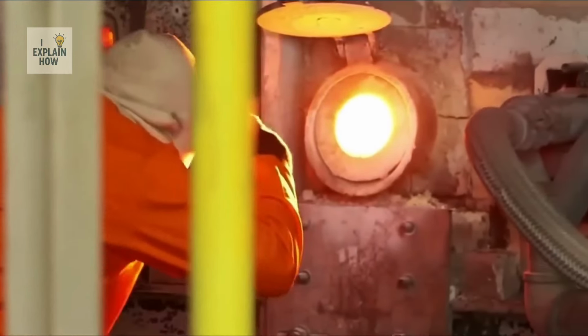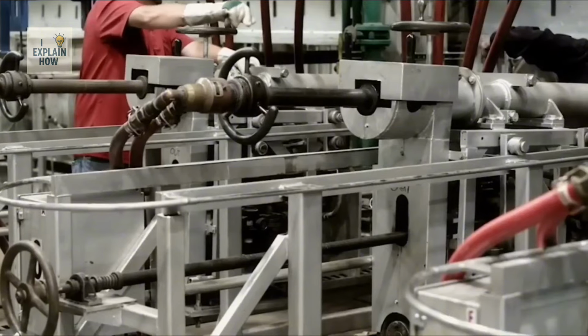The difference in density makes the glass float on the tin like oil on water. Thanks to gravity and surface tension, the mass spreads into a continuous, perfectly flat sheet of uniform thickness. The final thickness depends on the speed at which the glass is fed and the roller setting on the edges. When it leaves the bath, the glass is solid but still very hot.